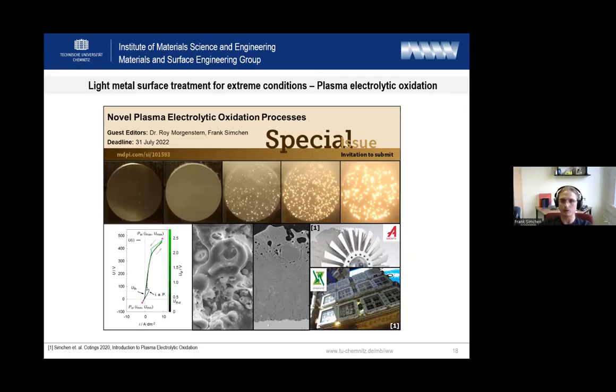Let's say fatigue is never good. Of course, this is what I wanted to say when I said it's a challenge which needs to be taken into account when you design the component. This turbomolecular pump is working very well over years of process time, and it's made of a cast aluminum silicon alloy. You should prevent too thin components. The crack could start anytime from the coating, but if the component is big and stiff enough, you will delay such reactions. So not every component treated by PEO will automatically break by fatigue. You just should take it into account when you design components with really thin wall thicknesses and in really demanding applications.